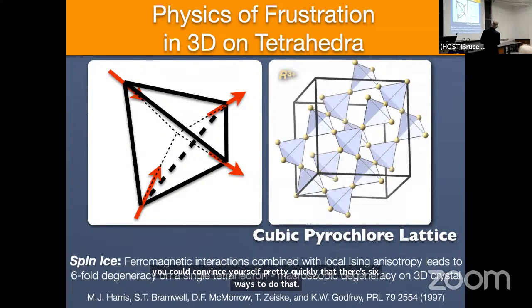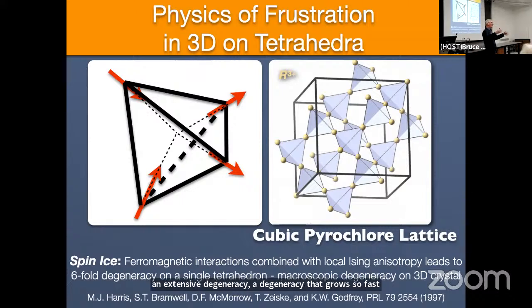And then if you join the tetrahedra together in this corner sharing motif to fill 3-dimensional space, you'll get, again, an extensive degeneracy, a degeneracy that grows so fast with system size that entropically you just cannot form an ordered state at low temperatures. Okay? And this is known as the spin ice problem. Okay, it's the problem that you get with ferromagnetic interactions and magnetic dipoles, where the local Ising-like anisotropy gives you the 6-fold degeneracy on a single tetrahedron.